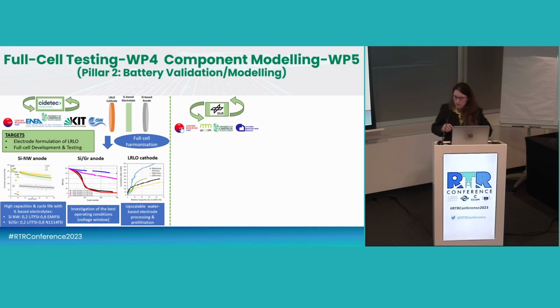They compare the performances of this full cell with what we can consider a kind of reference, that basically is a silicon graphite anode, that was our reference, and the performance of the cell we developed is far beyond the capacity that we can achieve with a silicon graphite anode. So again, we confirm that a 100% silicon-based anode can really outstand the performance when compared to a silicon graphite anode. Here then they also studied different kinds of pre-lithiation of the cathode with different formulations, again, with the aim of compensating the capacity loss of the anode and allowing a very good performing cell along a very long number of cycles.